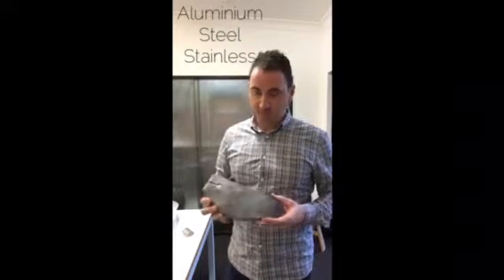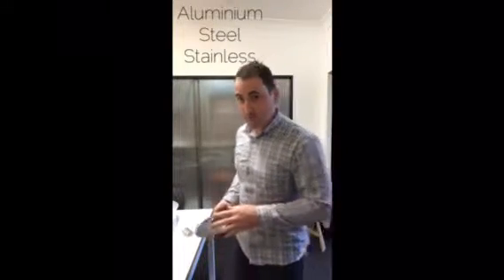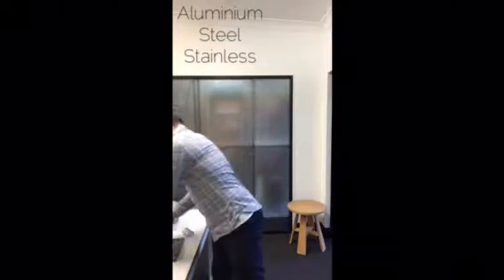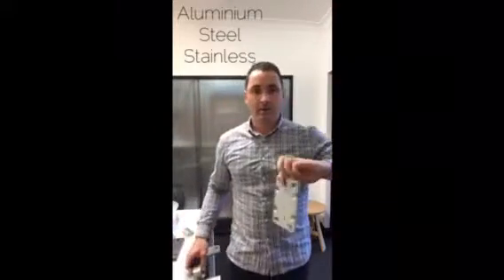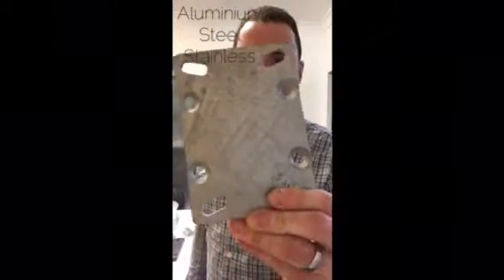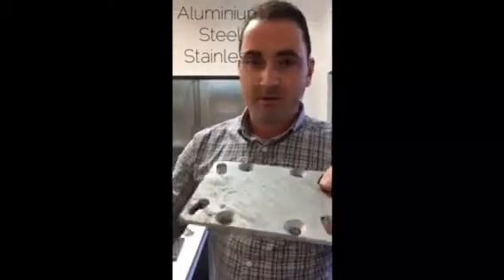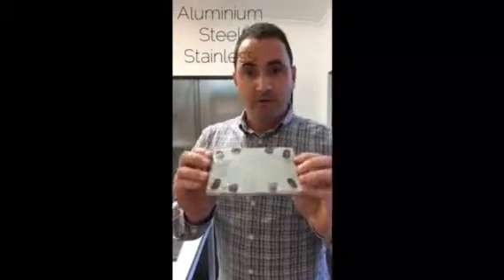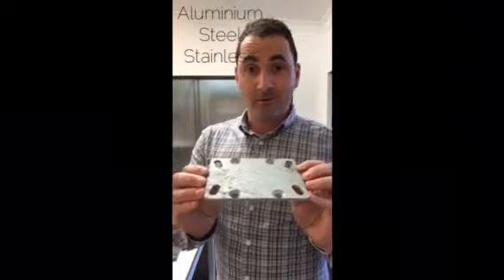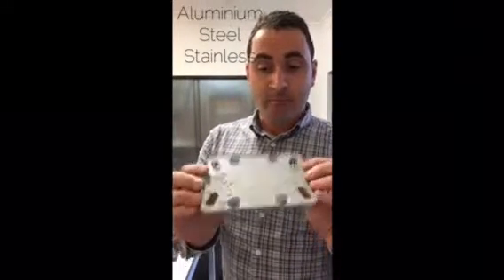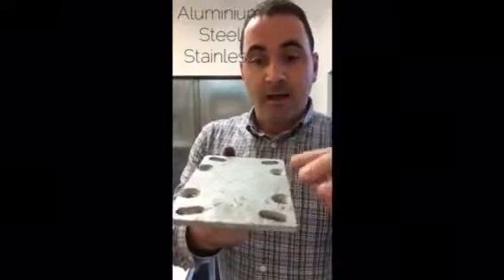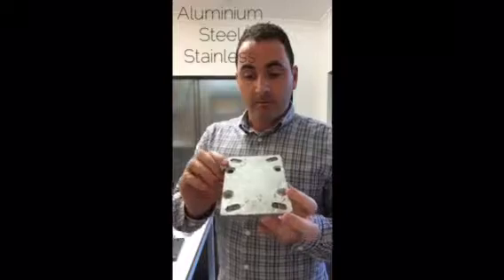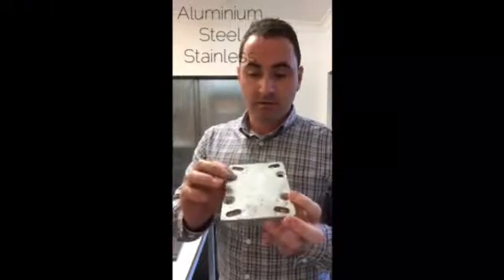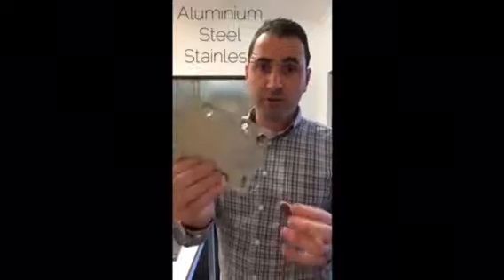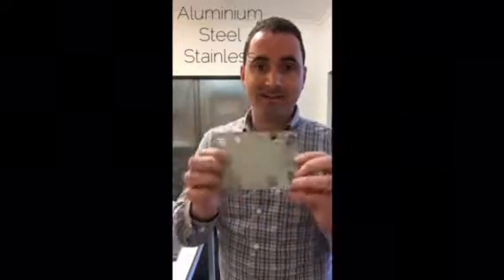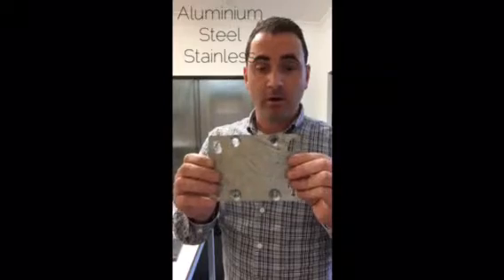There are two types of galvanizing that we kind of deal with. The main one is hot dip galvanizing. And this piece here has been hot dip galvanized, and this is a process by where we submerge the piece of mild steel into a bath of molten zinc and basically coats it in that zinc, which gives it a nice coating that's resistant to corrosion. Zinc doesn't readily corrode. Really durable finish. It can be dragged and scratched, and that zinc isn't going to come off. It's a nice thick coating that's on there.